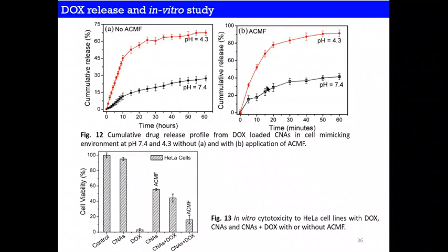And in blood, at 7.4, which is the blood pH, there is some release. This is one of the disadvantages, and it has not yet been rectified by the several studies. It releases drug molecules in normal pH also. But in lower pH, like the cancer cell environment of around 4.3, it releases a higher amount of drugs. And when you apply the ACMF, the drug release could be triggered to around 100%. So initially the drug release at pH 4.3 is 60%, but when you apply the applied magnetic field, the drug release could be triggered.